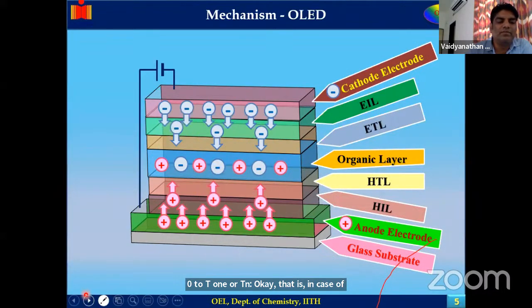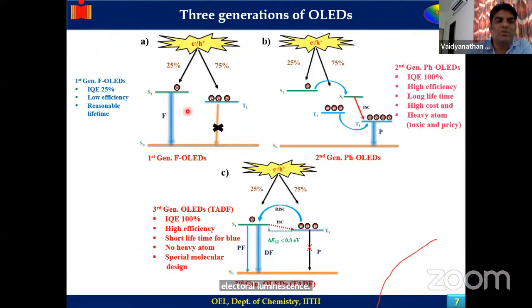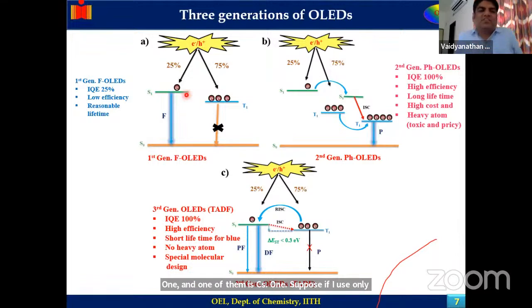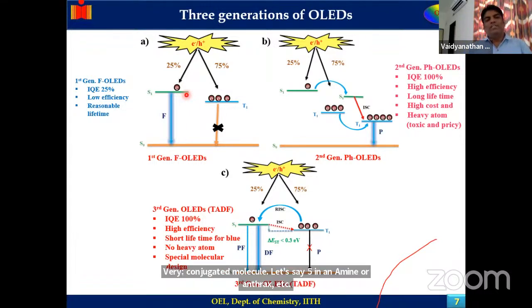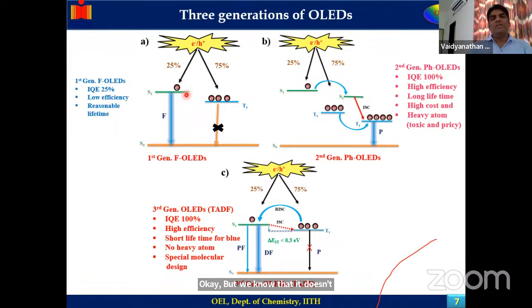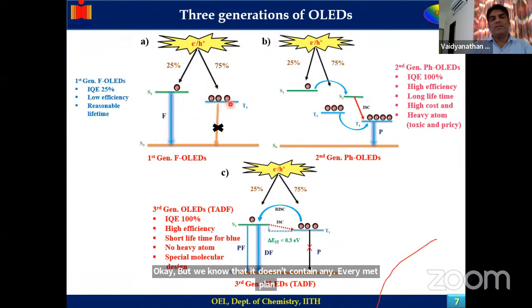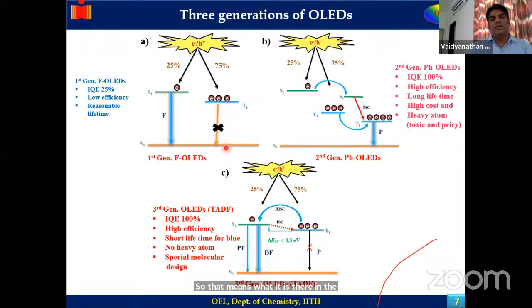electroluminescence, according to spin statistics, three of them are T1 and one of them is S1. Suppose I use only a fluorescent molecule containing only carbon and hydrogen, a very conjugated molecule, let's say triphenylamine or anthracene, etc. We know that it doesn't contain any heavy metal ion. So that means whatever is there in the T1 state cannot be taken to the S0 state. That means this state is completely negligible. Whereas the singlet state electrons can come to the ground state.